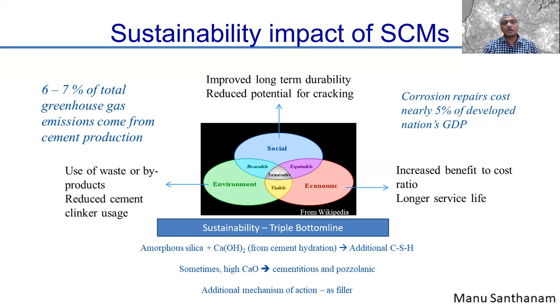Socially, you are producing a concrete that is going to be lasting for a longer time. Durability is high, as a result of which you have the potential for structures being in service for a longer period of time, and that obviously will have a major social impact. And that will also have an impact on the economy, because the benefit to cost ratio is going to be far exceeding that you can get from just ordinary Portland cement based concrete, especially when you're talking about chloride related problems, where it has been shown by years and years of research that use of supplementary cementing materials is a major, major thing to do to improve your resistance to corrosion.